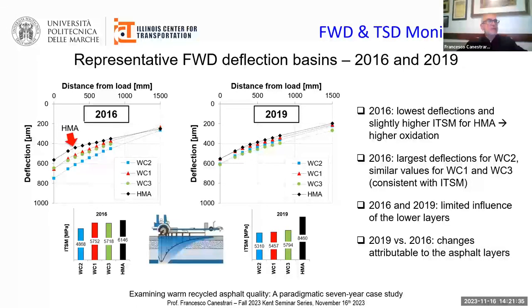The deflection at 1,500 millimeters from the loading plate is comparable for all test fields, both in 2016 and 2019, and remains almost unchanged over time, indicating a limited influence of the lower layers on the comparison between the test fields. Therefore, the general decrease in the deflections and the reduced variability between the test fields observed in 2019 can be mainly attributed to the changes of the asphalt layer properties.